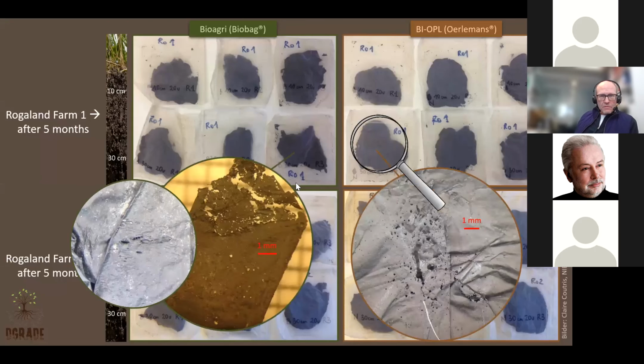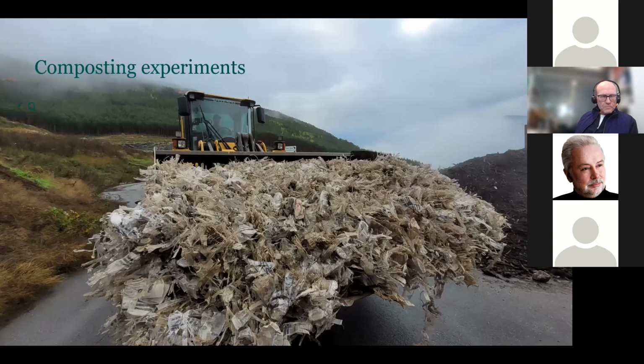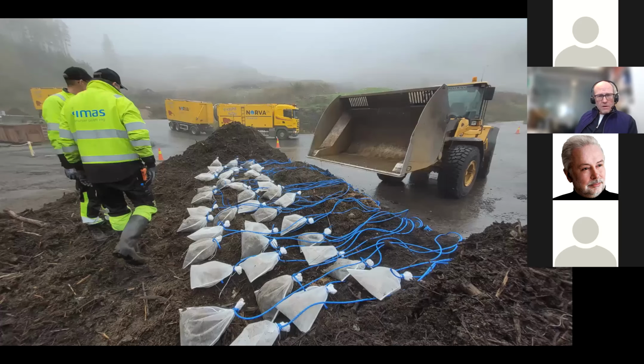You can see again how the plastic appears here when we take it out from the pouch, and there is clearly some fragmentation going on, and degradation has started, but it's far from efficient. We also did some composting experiments. This is PLA drinking glasses from music festivals that are recycled by a waste company that we collaborate with. We use the same mesh bag technique, but here we also fill these pouches with compost.